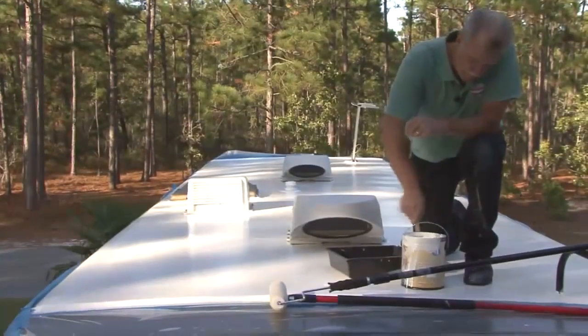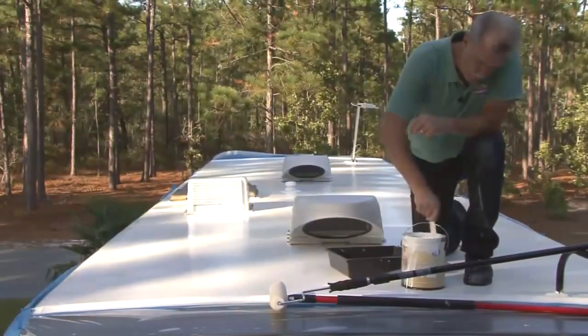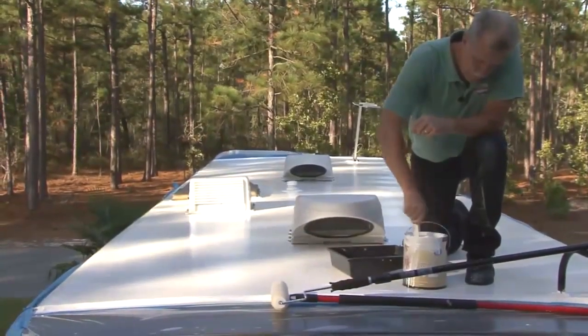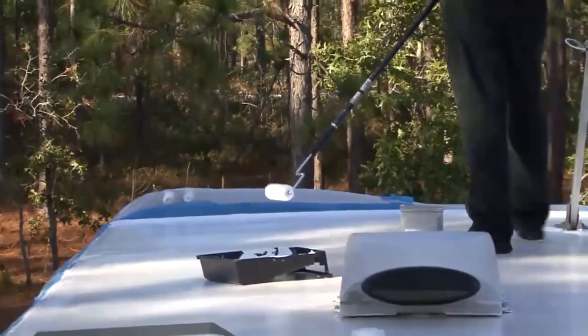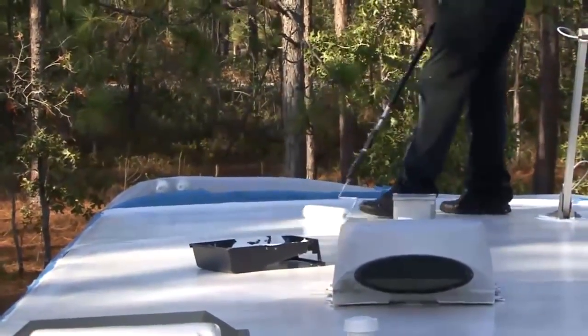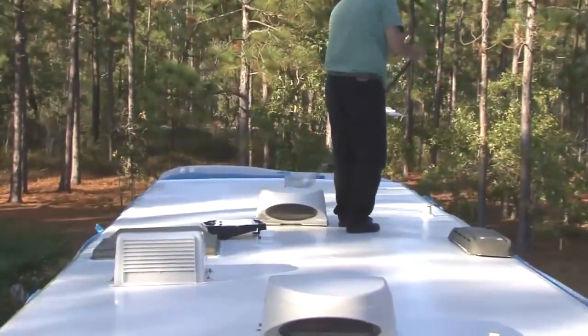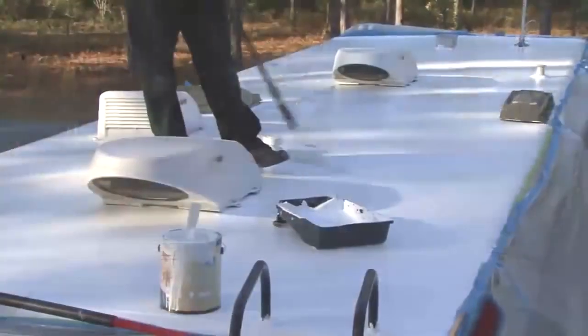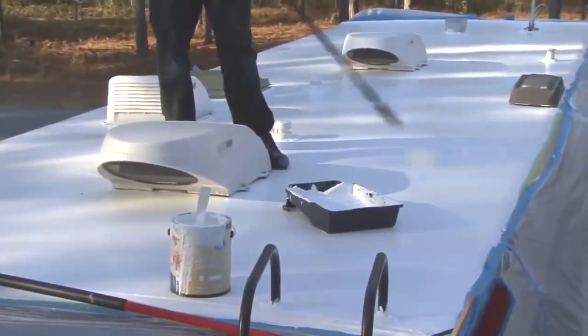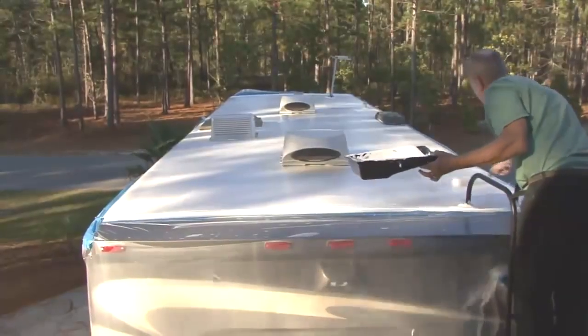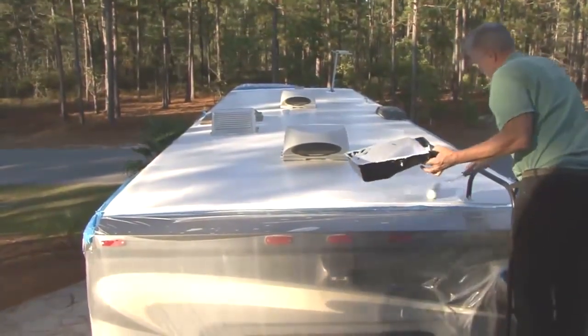The first coat must be dry before the second coat is applied. Under normal conditions of 70° Fahrenheit and 50% relative humidity, the second coat may be applied within 1 to 2 hours at the same rate as the first coat. After applying the second coat, you should allow for a minimum of 3 hours of direct sunlight prior to nightfall. It takes 24 to 48 hours for the coating to completely dry and cure. Make sure no rain or heavy dew is allowed to come in contact with your newly coated roof during this time period.